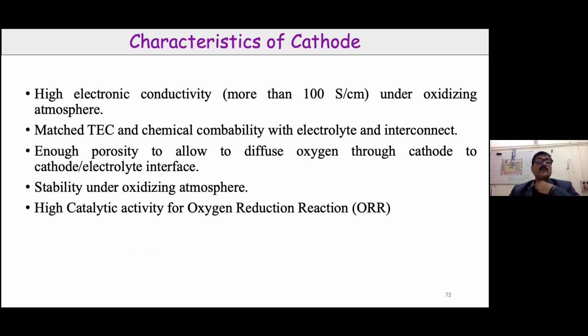Now we also worked on a few cathode materials. The cathode needs very good electronic conductivity, and as I said, the thermal expansion coefficient should be matched. It should have enough porosity to allow oxygen to diffuse through the cathode. Of course, anode and cathode should both have good porosity and should not be very dense. Otherwise, the hydrogen gas on the anode side and the oxygen gas on the cathode side will not be able to reach the reaction level. So they should be porous in nature. For the cathode, there should also be stability under oxidizing atmosphere and high catalytic activity for the oxygen reduction reaction, so that oxygen can be reduced to generate oxide ions.